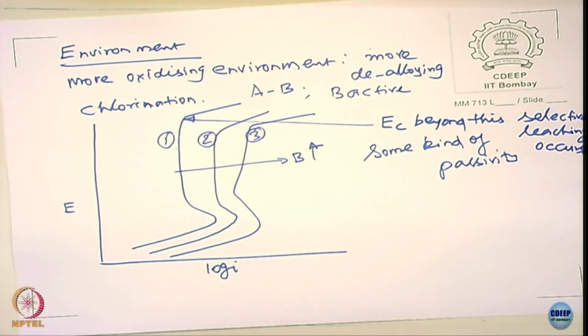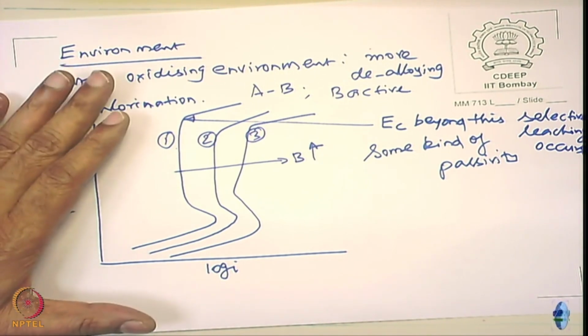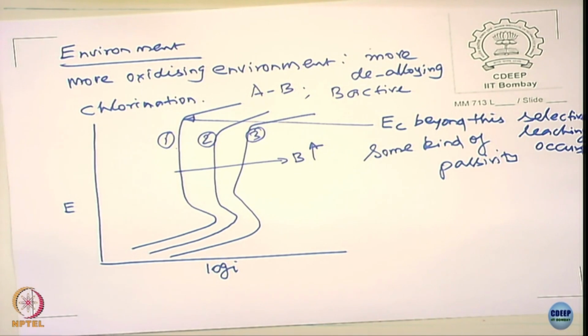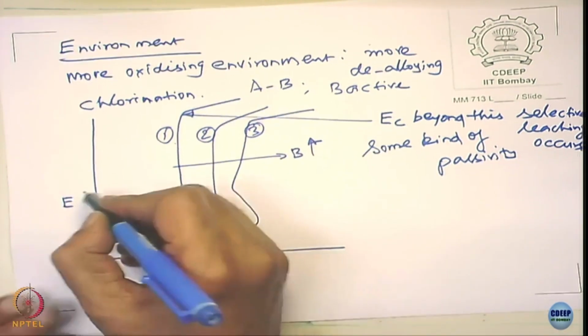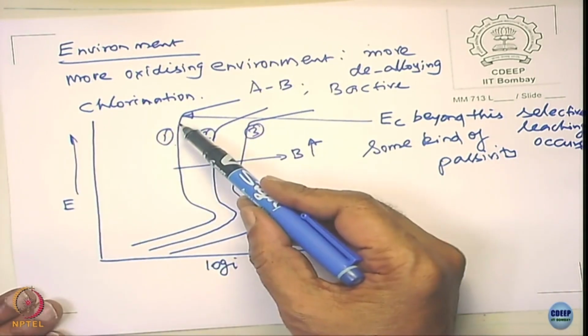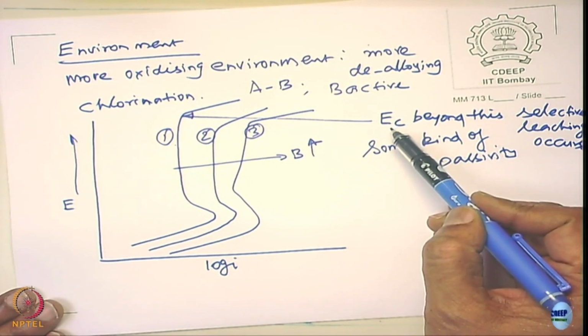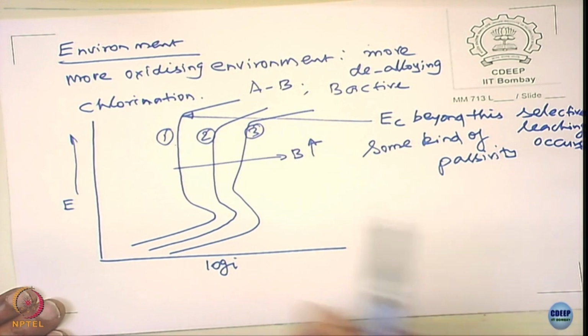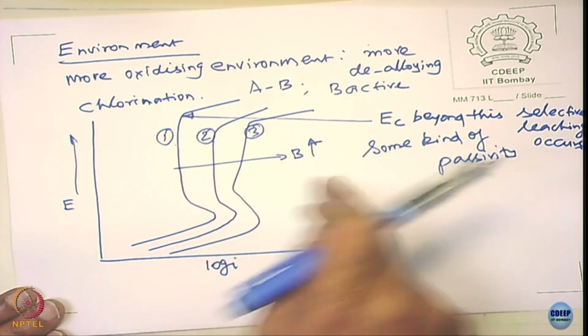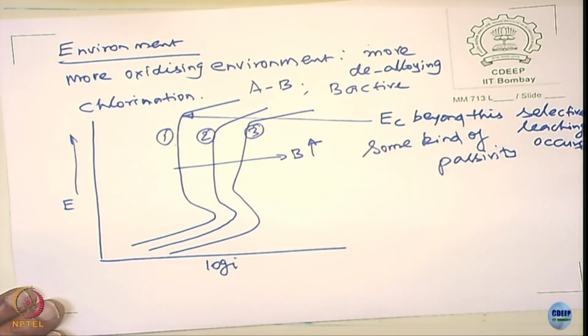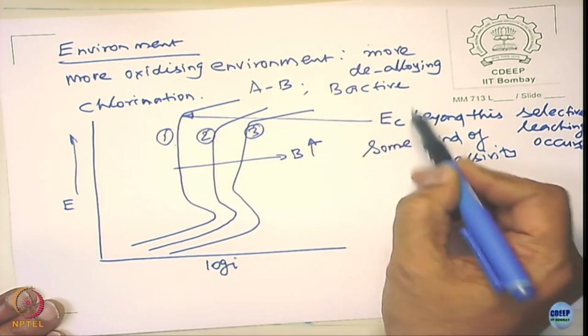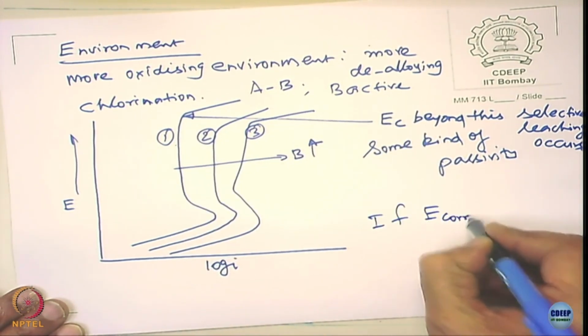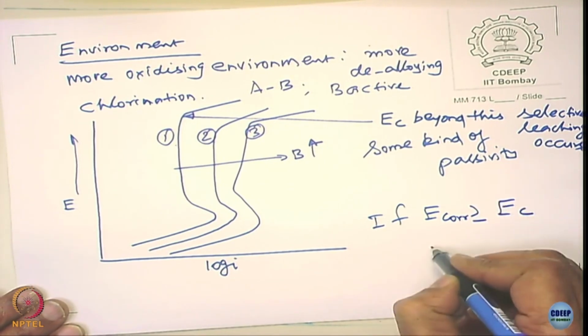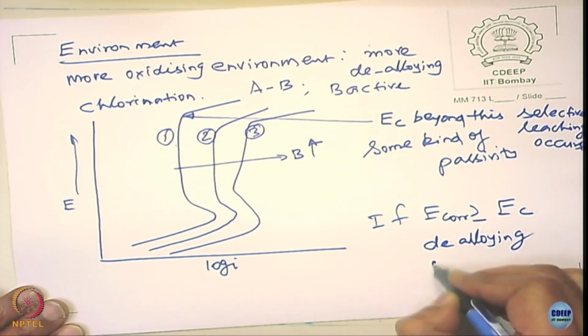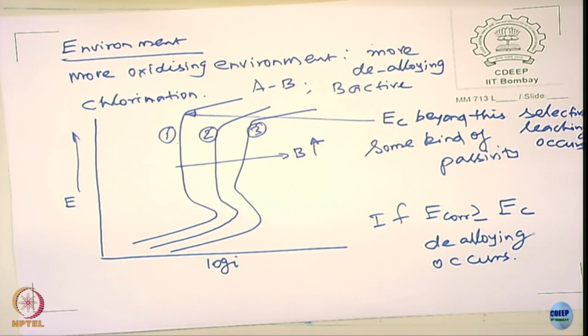So, there is a driving force for corrosion to occur, right. So, for these alloys, in order to find out whether they undergo dealloying, how effective they are, you can carry out a polarization curve, okay, and get this and find out what is the EC value. EC here represents the potential above which the dealloying really occurs. And the increase in passive current density here means that there is more dealloying taking place. Now, if the corrosion potential exists above EC, if Ecorr is going to be greater than or equal to EC, then what happens? Dealloying occurs, right or not? Because only above EC you have dealloying, you get these polarization curves.